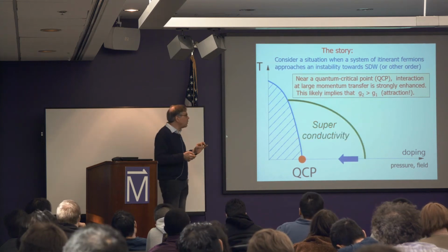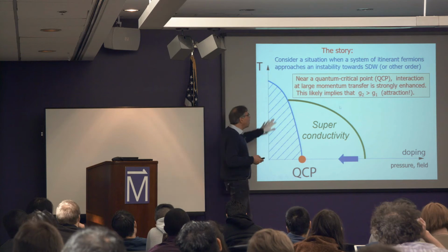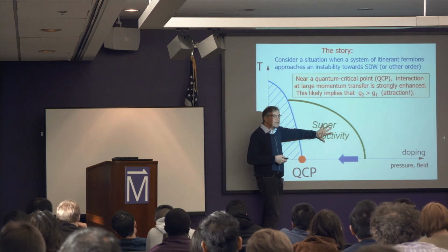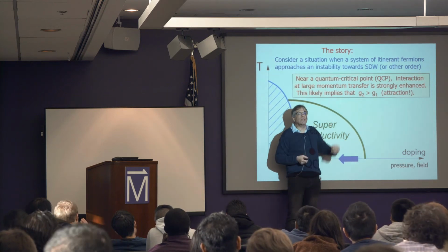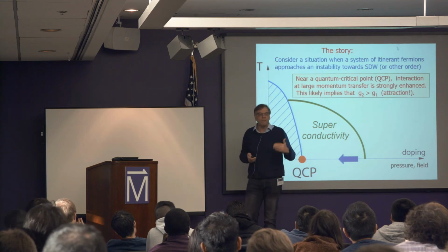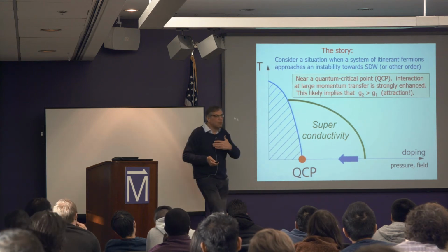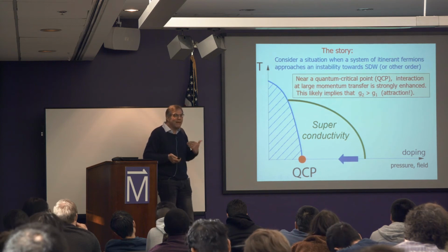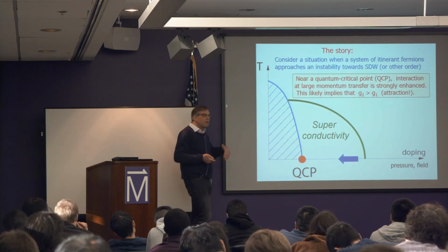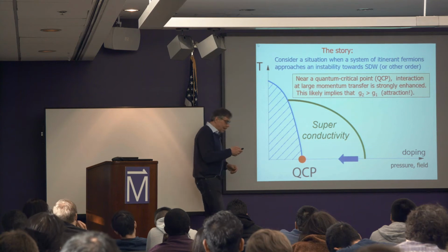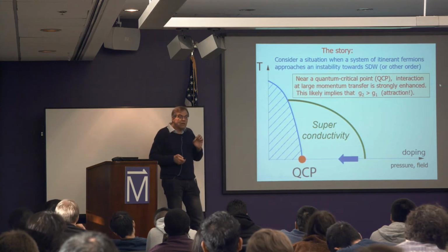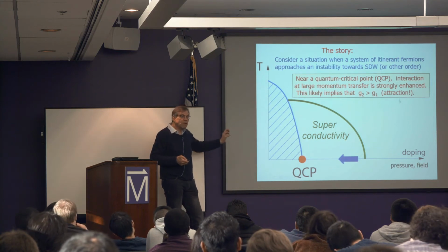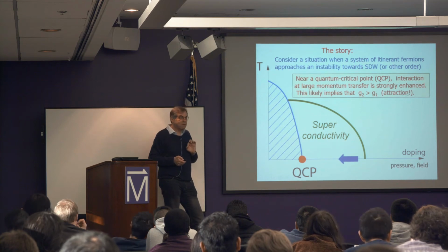Then obviously what we expect is that somewhere here the system will become superconducting, because I made the interaction attractive in a particular channel. In cuprates it's d-wave, and in pnictides it's s plus-minus, but I made it by hand, using the physics argument. But from this point, the story becomes interesting in another aspect.